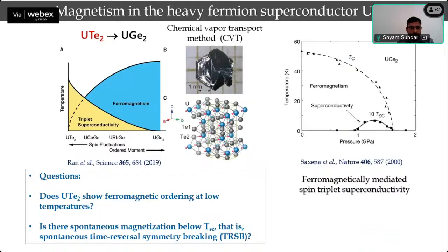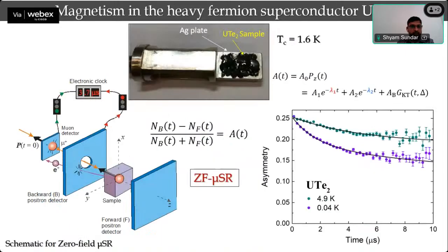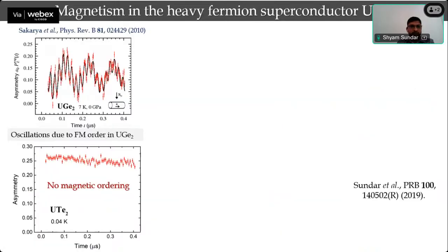With these two motivations, we studied this material using zero field muSR measurements. These are the samples mounted on the silver plate, and we did the zero field muSR measurement. Zero field means, as I said, we do not apply any magnetic field. We place the sample, we put the muon into the sample, and we detect its decay into a positron either in a backward or in a forward counter, and we get the asymmetry, which we plot as a function of time. We fit this data using an appropriate model, where we get lambda 1 and lambda 2 as the relaxation rates as a function of temperature.